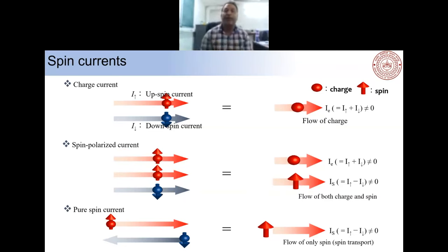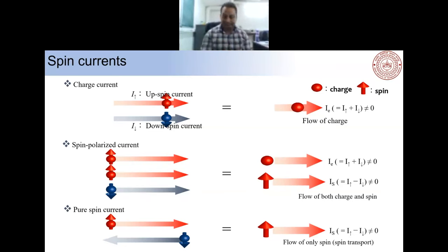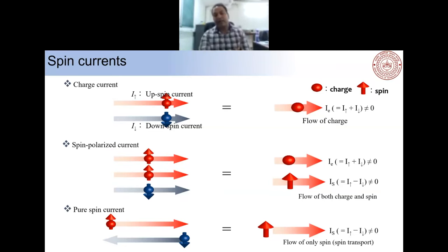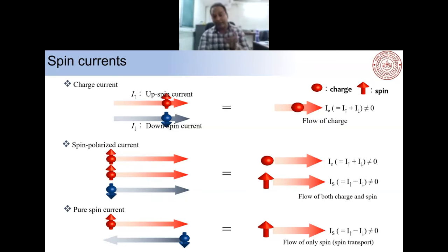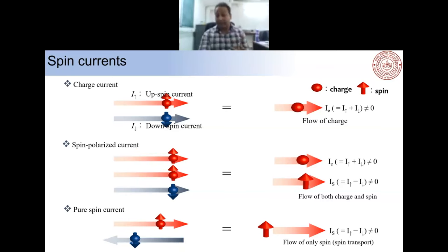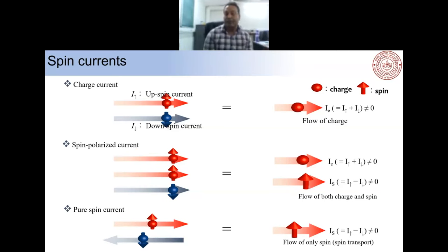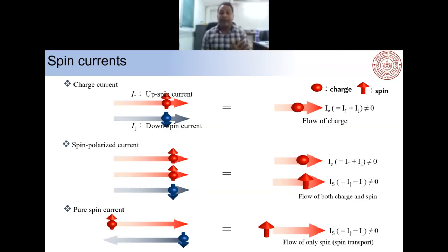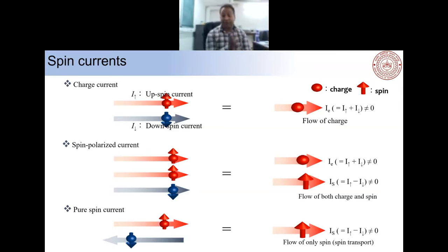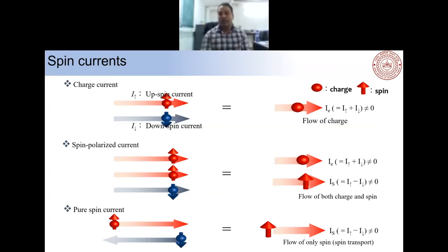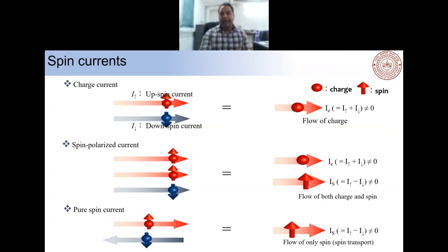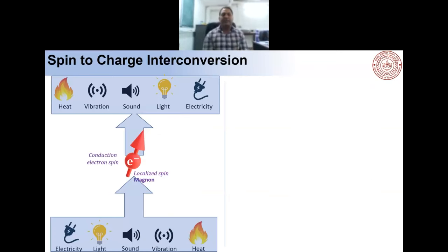Third, there is another phenomenon: spin-orbit coupling. In materials with high spin-orbit coupling like platinum, we can pass an unpolarized current and get two different polarizations for up-spin and down-spin, resulting in two different propagation channels. As a result, there is only the flow of angular momentum with no net charge flow — this is a pure spin current. We can generate spin current by several means: electricity, light, sound, vibration, and heat.